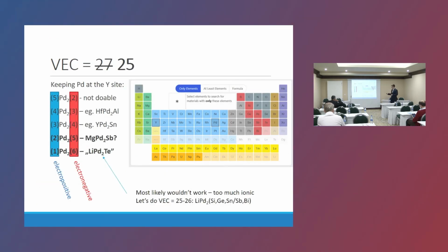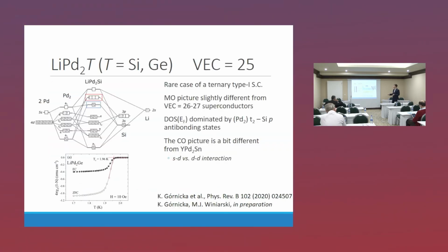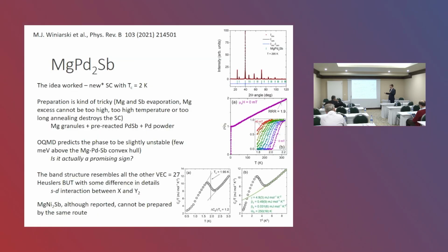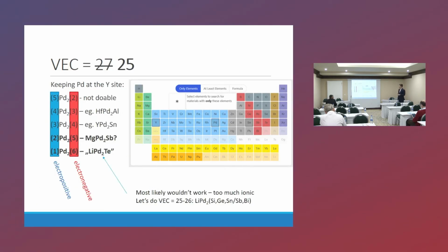The preparation is kind of tricky. However, we were able to make it pure and superconducting. The nickel one cannot be synthesized for now, even though it's reported. Nevertheless, our anti-bonding plus electron count approach has worked. So how about replacing that further with lithium? It wouldn't work for 27 because we would have to use something like tellurium, which is going to form an electron charge transfer pair with lithium, forming an ionic-bonded lithium telluride plus palladium.